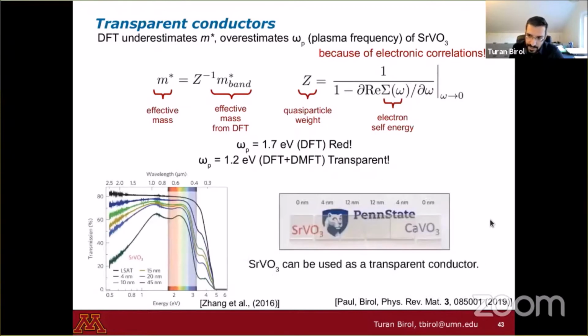And it turns out that these transparent conductors are very exciting for engineers. Electrical engineers' mouths water when you talk about a transparent metal, because for various applications, we need good conductors of electricity that are also transparent to visible light. And experiments really confirm this prediction that the plasma edge of strontium vanadate is at around 1.2, 1.3 eV, and you can really see through it to a great extent. And what you see here is the substrate. You don't even see the film on typical screens.